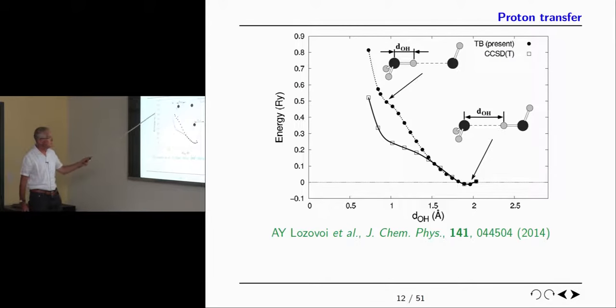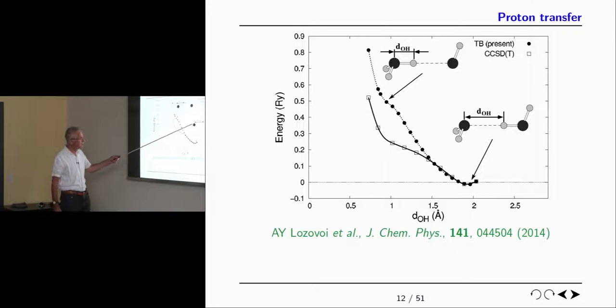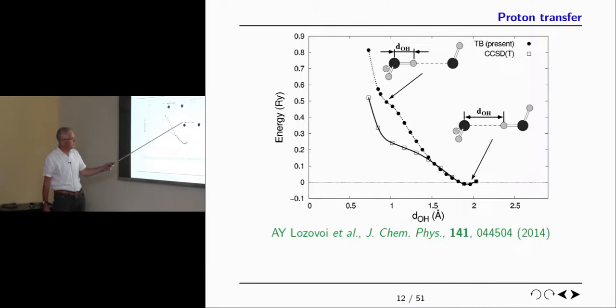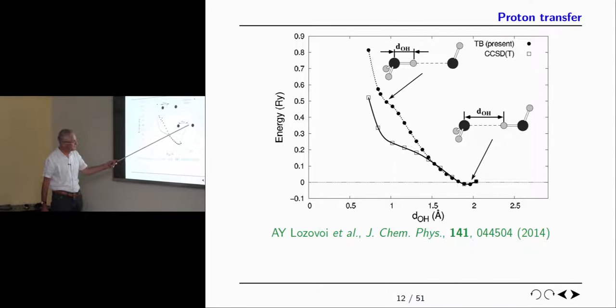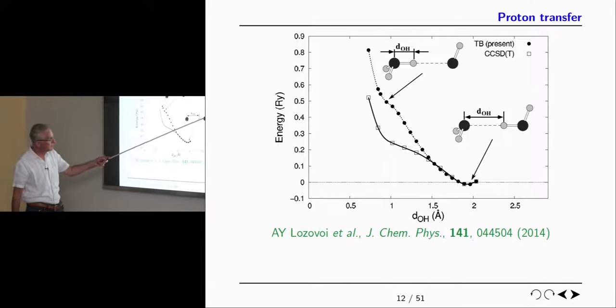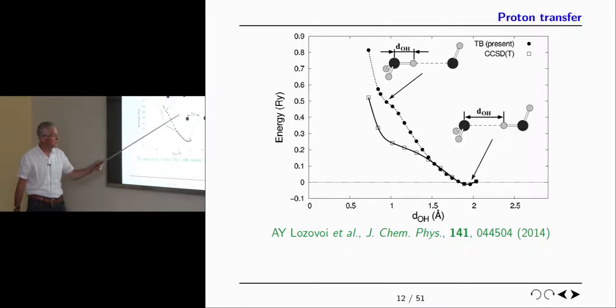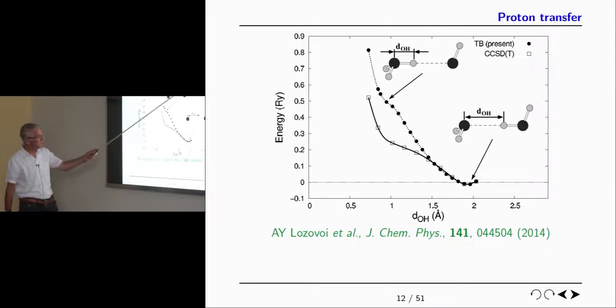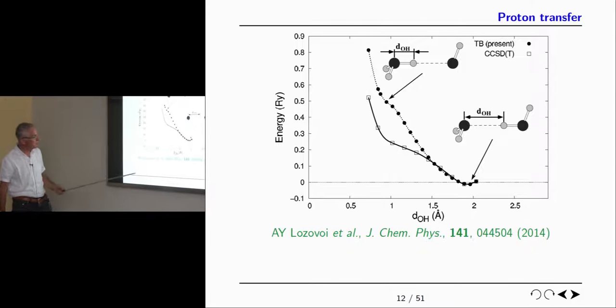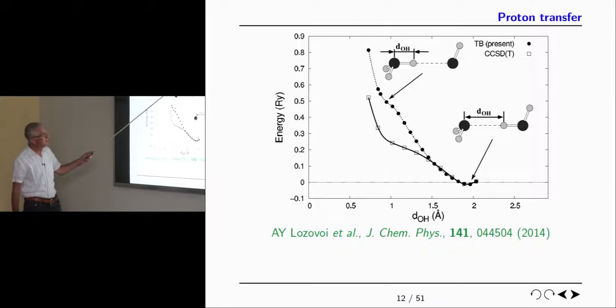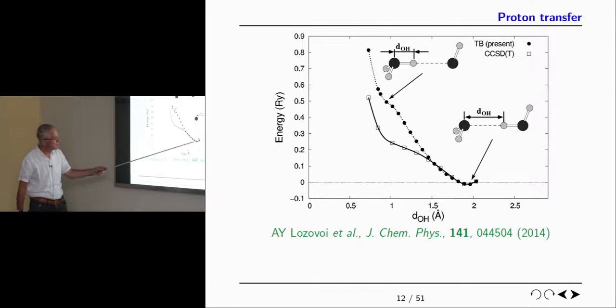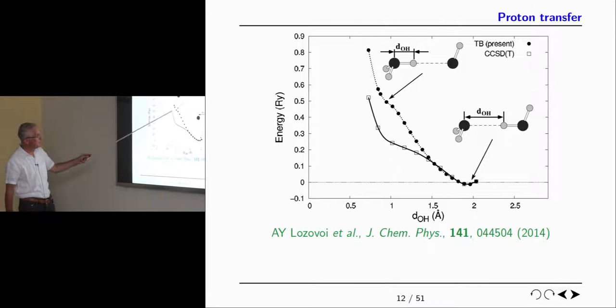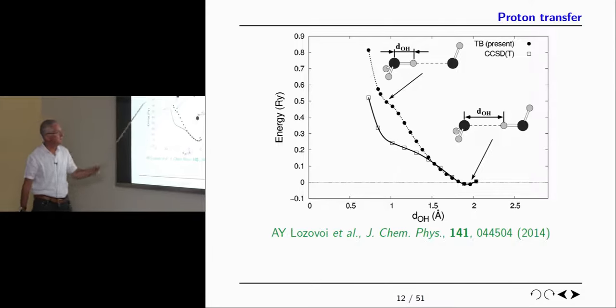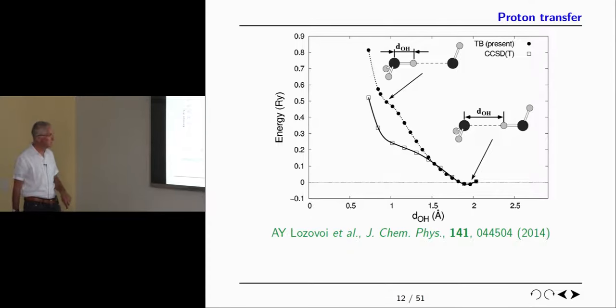And we were able to look, for example, at hydrogen transferring. So we start with two water molecules in the ordinary sense in a water dimer, and we grab one of the protons. In real life, they're not exactly in a straight line. As I said, there's this angle alpha, which it lays off. It's called a nonlinear hydrogen bond. And we just drag this thing from one side of the system to the other. So we end up with an OH minus and an H3O plus. And the energy to do that, calculated in the tight binding model, looks like that, and it compares not bad. We're quite happy with that compared to a coupled cluster singles, doubles, triples calculation in quantum chemistry.